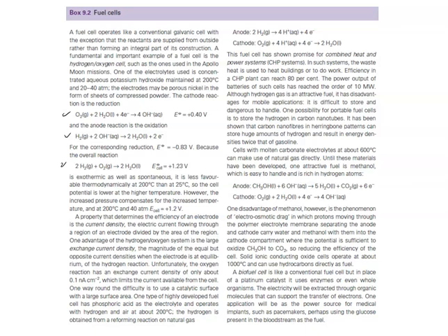A property that determines the efficiency of an electrode is the current density, the electric current flowing through a region of an electrode divided by the area of the region. One advantage of the hydrogen-oxygen system is the large exchange current density, the magnitude of the equal but opposite current densities when the electrode is at equilibrium, of the hydrogen reaction. Unfortunately, the oxygen reaction has an exchange current density of only about 0.1 nanoamps per square centimeter, which limits the current available from the cell. One way around the difficulty here is to use a catalytic surface with a large surface area.